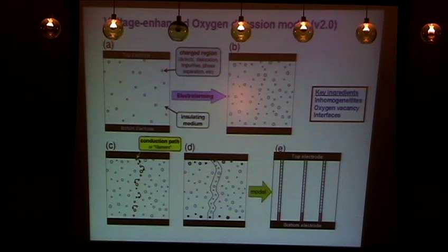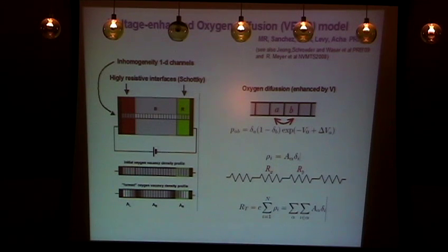So the idea will be just to have this conductive path going through the sample, and we're going to model one of those. So the model is like this. It's very simple. It's just a linear one-dimensional path in which we're going to split it into different beams or domains that go through the system. This is characterized by three regions: one bulk region, and then two interfacial regions where the resistance is much, much higher. We know that the resistance in the interfaces is what really controls the two-terminal resistivity of this system.